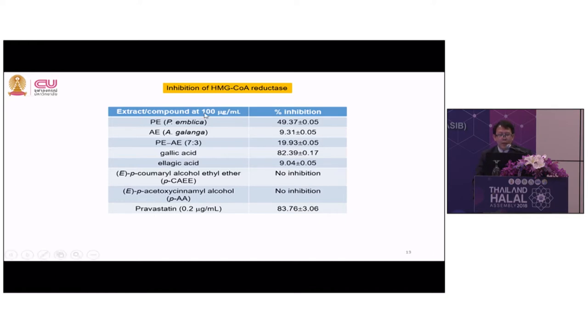And this table shows that Phyllanthus emblica and Alpinia galanga have percent inhibition of nearly 50% and 10% respectively, whereas the combination has about 20% inhibition, and the gallic acid contained in Phyllanthus emblica is a key chemical that has this effect. The chemical constituents in the galangal did not inhibit the enzyme. So we can conclude that Phyllanthus emblica contributes the inhibition of this enzyme.